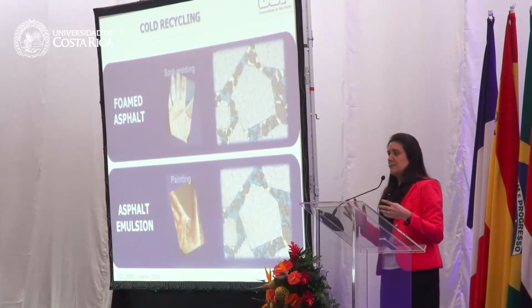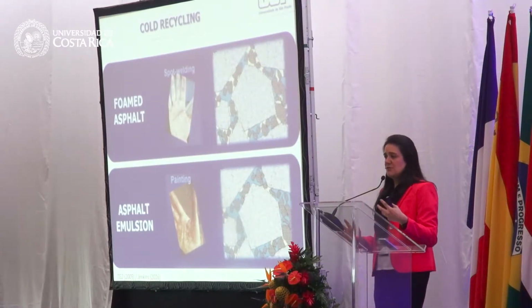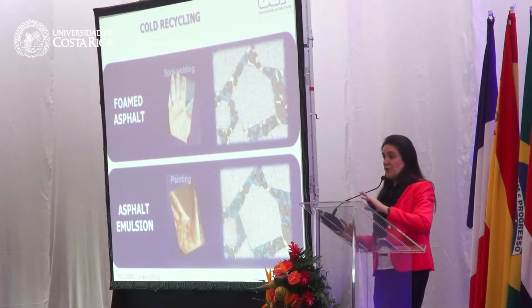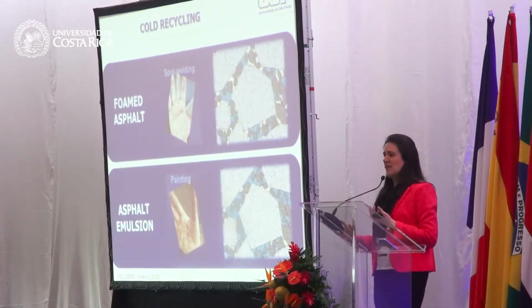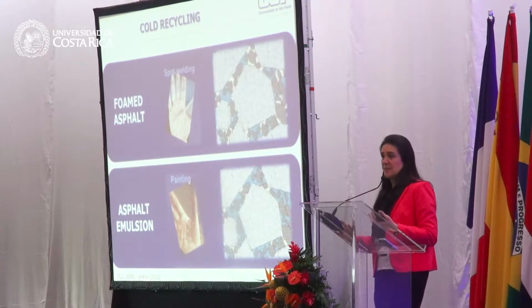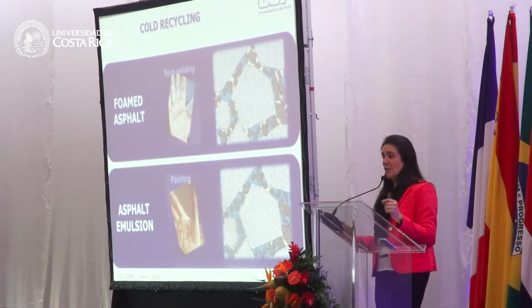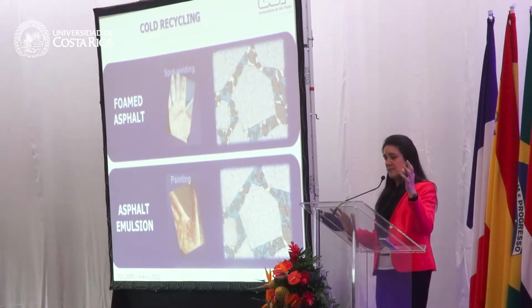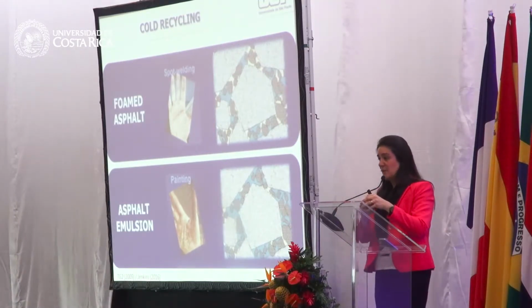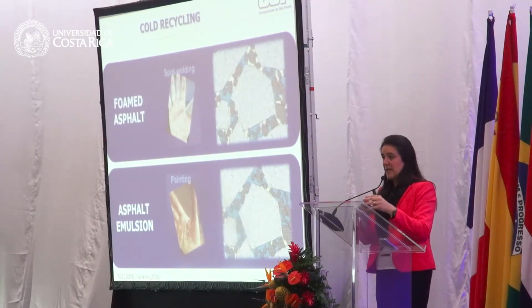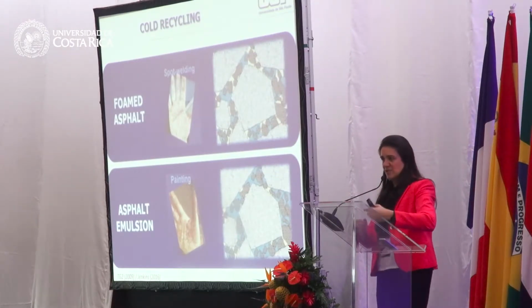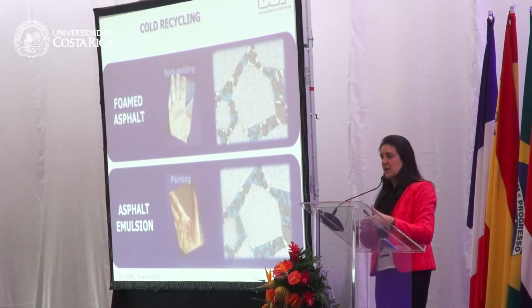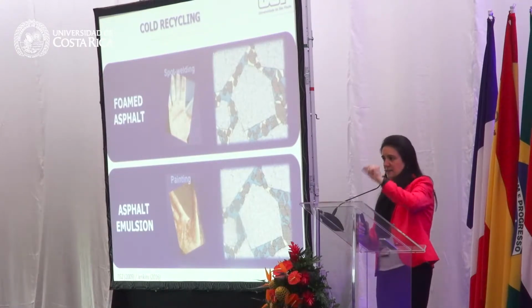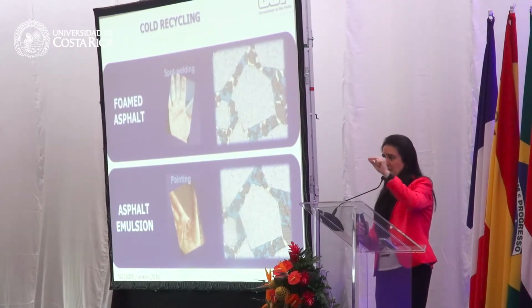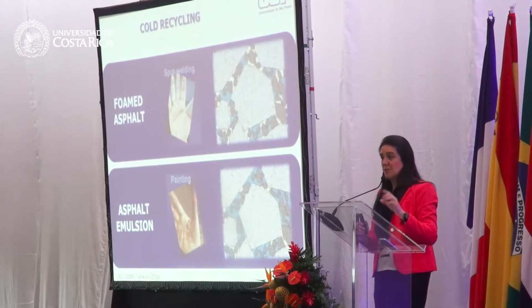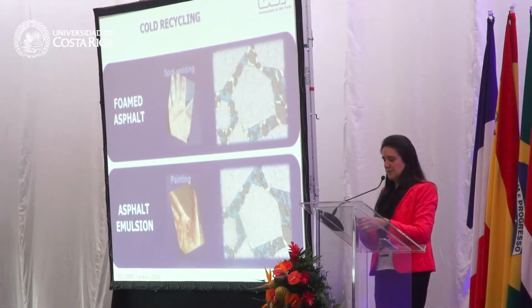So in the emulsion process, what we normally have is a more uniform painting of the aggregates that is facilitated by the water. In the foaming process, the foamed asphalt sticks together with the fine particles, and if you make a cross-section on a lab-prepared specimen, you see a couple of spots with black marks from the asphalt binder. So it's not uniformly distributed.